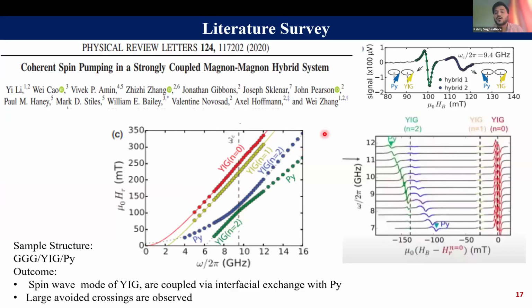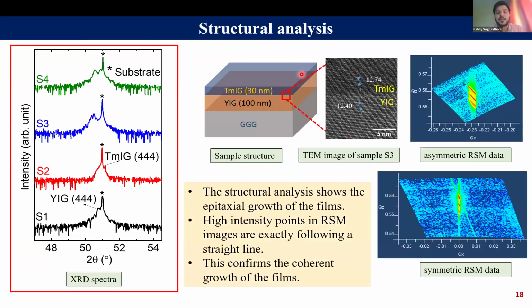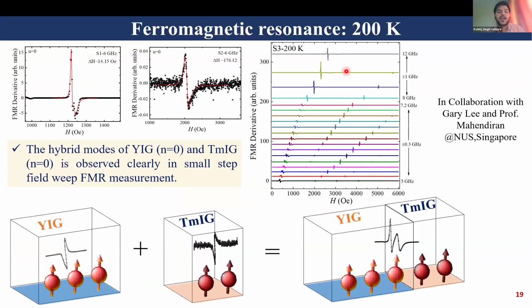And apart from this, the broad spectrum of the hybrid modes at the higher frequency, of out of phase YIG and permalloy, signifies this coupling could be an antiferromagnetic coupling because of the magnon coupling. So for this, we have taken our samples of the YIG and TMIG bilayers, which are grown epitaxially and coherently, confirmed from the RSM and TEM images, for ferromagnetic resonance spectroscopies at different temperatures. At 200 Kelvin, we found that our hybrid mode gives some kind of signature of magnon coupling in our system, where the Kittel mode of YIG is getting coupled with the TMIG mode and producing this hybrid mode.